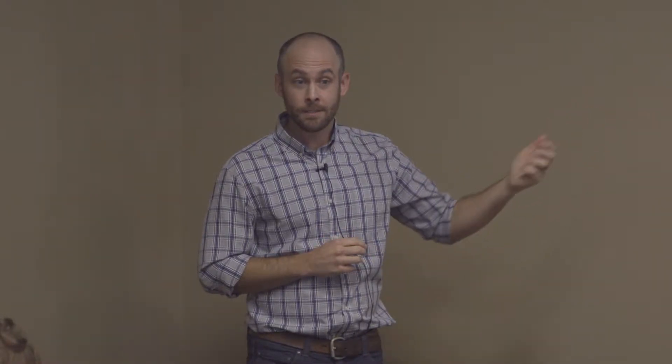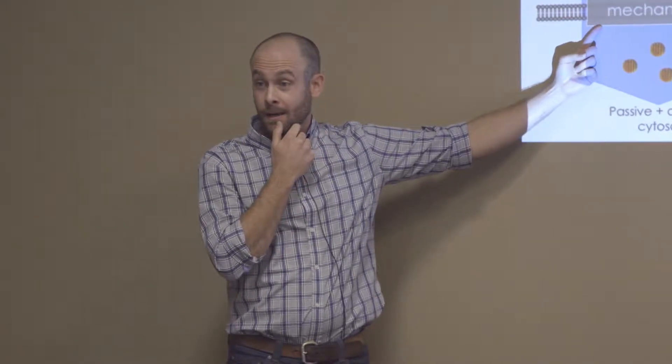What are we doing? We're collaborating with a professor at EPFL in Switzerland whose group makes gold nanoparticles maybe 2-5 nanometers in diameter coated with amphiphilic ligands. These particles readily go into the cell and diffuse everywhere, whereas particles with less balance between hydrophobic and hydrophilic tendencies only get taken in through endosomal uptake where the cell sequesters and breaks them down. They haven't found any toxic effects. The inspiration is can we make better drug delivering technologies? We've partnered to use our droplet interface bilayer to understand how these nanoparticles interact with the membrane.